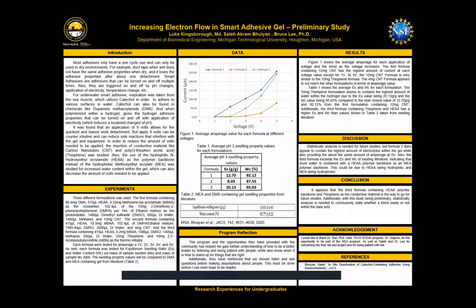So all in all, it appears that thiophene, because of its higher electrolyte content, just through its swelling properties, and the fact that at 5 volts, it's almost the same as the 12 milligrams of CNT, appears to be the way to proceed with this experiment and for future studies as well.